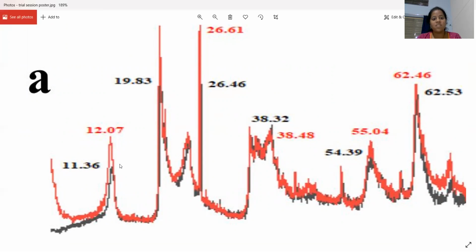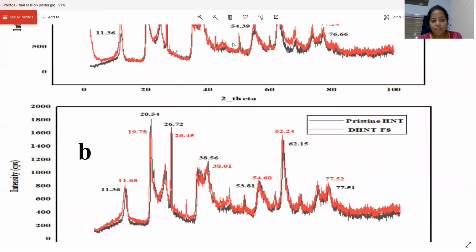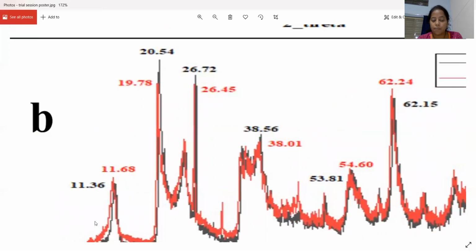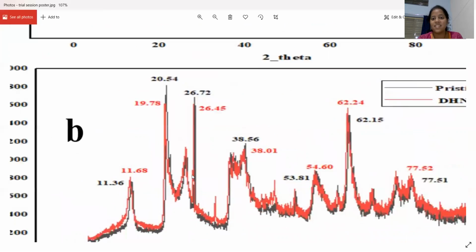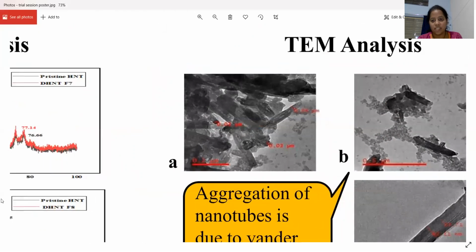Upon doping, the F7 sample exhibited a slightly broad peak at a higher 2 theta value of 12.07 degrees, and this is attributable to the influence of speed and the temperature generated during the homogenization technique. Whereas the F8 sample exhibited a sharp narrow peak but at a lower 2 theta value as compared to the F7 sample, at 11.68 degrees, and this indicates the slight doping of pristine HNTs.